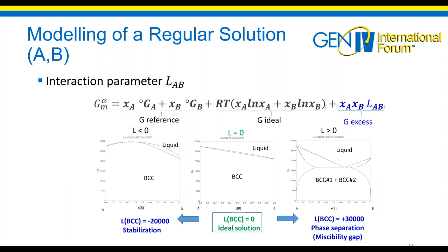But in your system, you're also taking into account liquid phases. And so we also need to model the Gibbs energy. And of course, a liquid cannot be modeled as a solid, because the constituents have no fixed environment, and also the number of nearest neighbors can change in a liquid. So I will not go into details, but you can describe the G function for liquid with three terms. So one term called the G reference, another term called the G ideal. So this is if you have a liquid that is taken as an ideal solution, so there are no interactions between the compounds in solution. And what we call a G excess, that is representative of these interactions with an interaction parameter L.